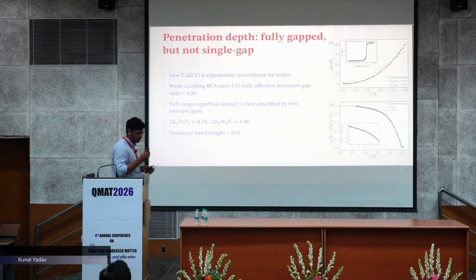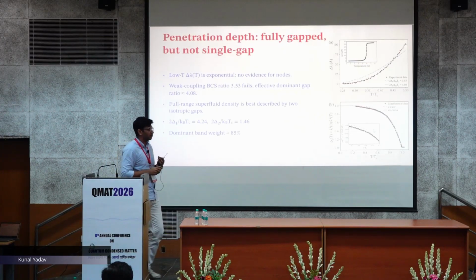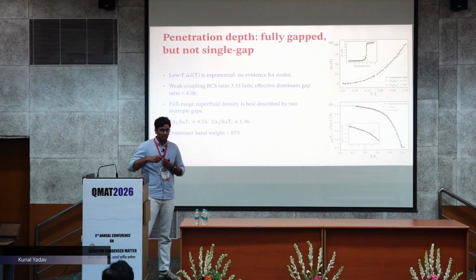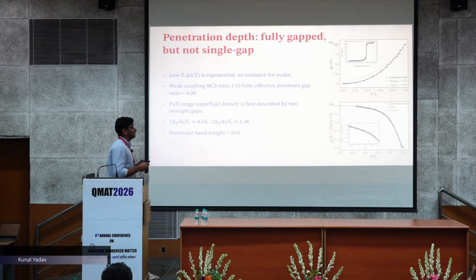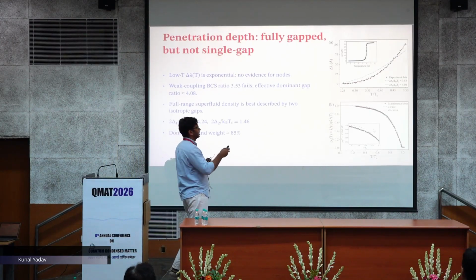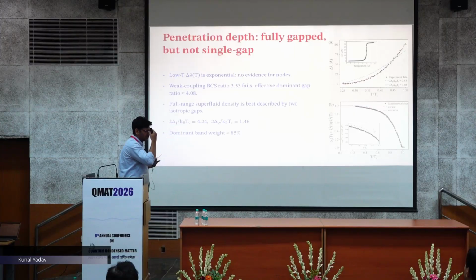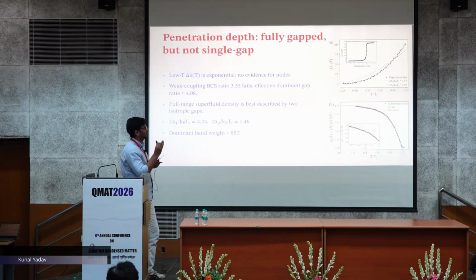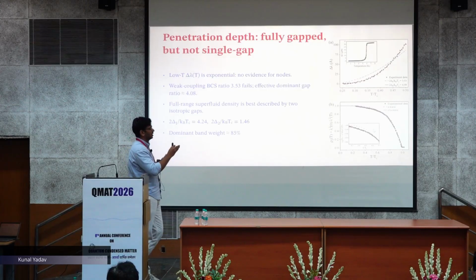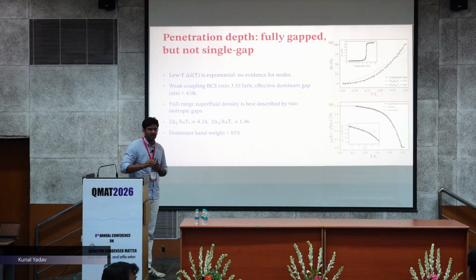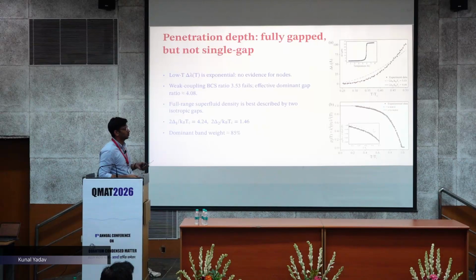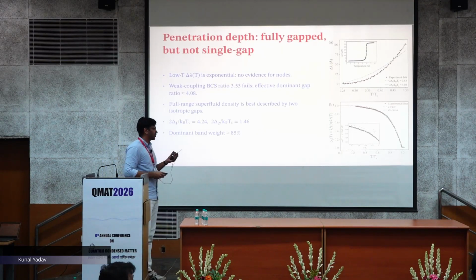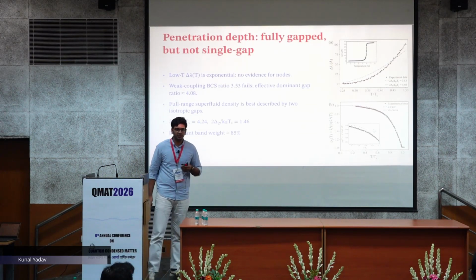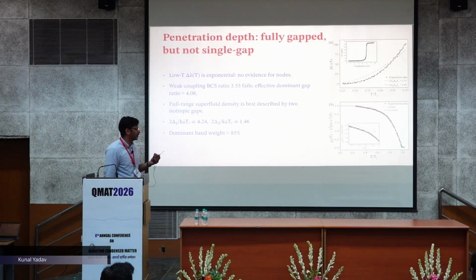And then we have done the penetration depth measurement. The penetration depth measurement also indicates that it is an S wave, a fully gapped superconductor, but it is not a conventional fully gapped S wave superconductor, because for a conventional S wave superconductor the value should be 3.53, but the fitting shows that the value is 4.08. Then we have done the measurement using the superfluid density, using the penetration depth measurement, which shows it is an S plus S wave superconductor, which means it is a multiband superconductor.